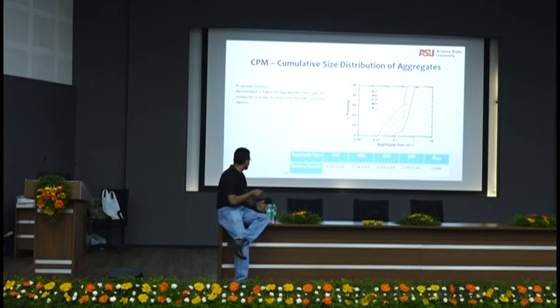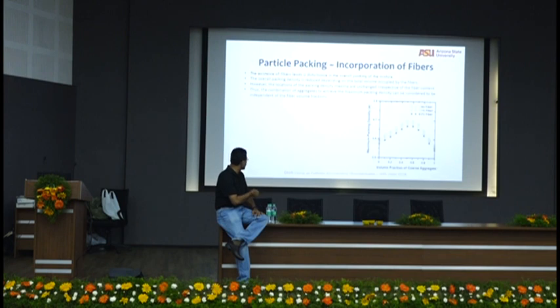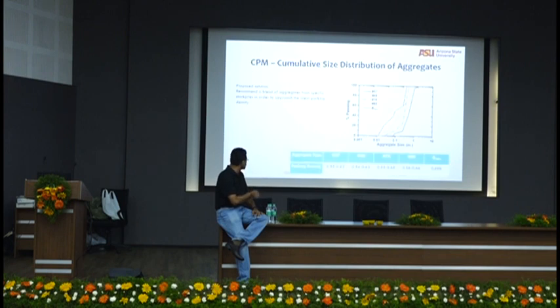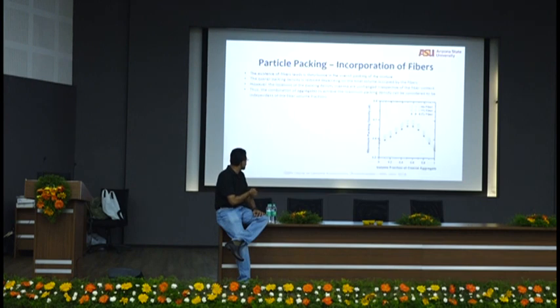57 is very common. Look at typical packing densities of those aggregates, right? If I choose a standard number 57 stone that they use for regular concretes, my packing density is only 0.55 to 0.60. With 89, I get up to 0.66. But here I get up to 0.696, which is the higher packing density. And then you put in fibers, and when you put in fibers in an already packed mix, the packing density goes down because these long fibers try to push the aggregates away, right? So they create more space. So you have to account for that also.